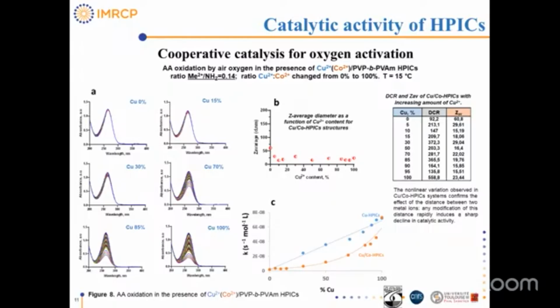It's necessary to say that, like copper, cobalt can complex with amine functions, but it doesn't catalyze ascorbic acid oxidation. So cobalt was a very suitable object to modulate different distance of copper ions. As we can see from figure 8a, the best efficiency is observed for the HPICs containing 100% copper ions. In the presence of cobalt ions, catalytic activity is decreased.